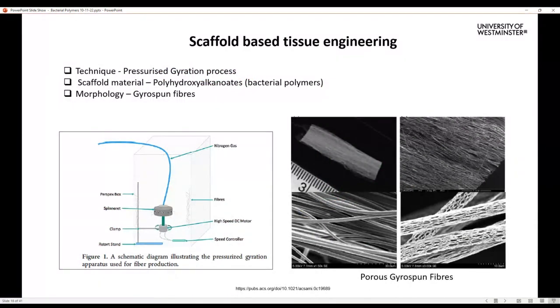So we then moved on to another project where we used these polymers to create these nice fibrous structures. So for the first project, we created nice tubular structures and used that as a nerve implant. For this project, we created these nice fibrous structures. The technique that we used was called pressurized gyration process. It's very similar to how we make candy floss. So there's this cylindrical vessel with lots of pores around it. So we apply pressure and agitation, and then we collect these fibers.